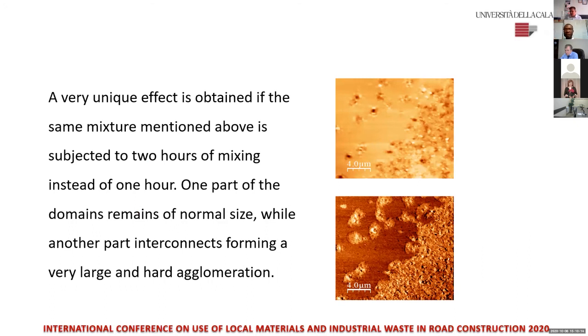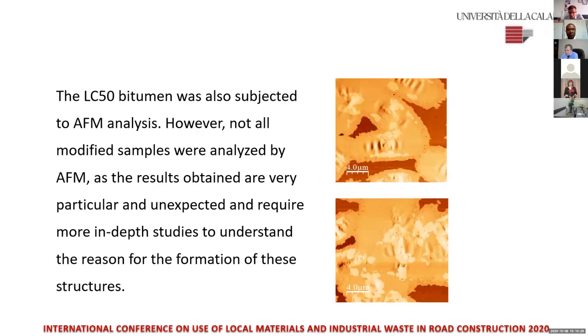It's better to prepare your samples around 1 hour. It's better not to leave them for about 2 hours because you ruin the domain structure on a microstructural level. So the LC50 bitumen, which is the stronger bitumen, the 50-70 penetration grade, we also analyzed under the atomic force microscope. You can see that it has more asphaltene domains. This is the hard part, and this dark part is the soft part, the oils, the maltenes, and all of that. While these are the asphaltene domains, you can see that it has a higher penetration grade, which is 50-70, which makes it stronger.